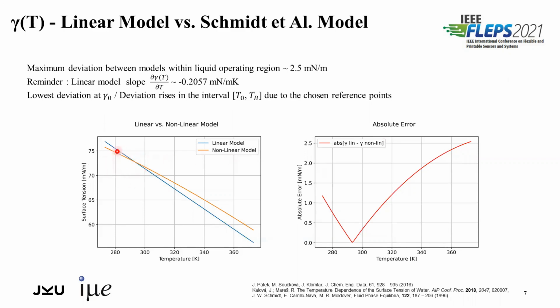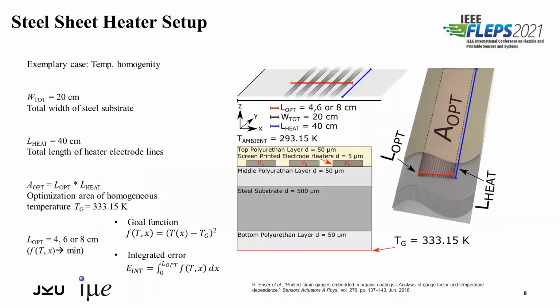And the lowest deviation is in the region of gamma 0, because this is one of the reference points for the nonlinear model. And the maximum deviation here is about 2.5 millinewton per meter, where the slope of the linear model was about minus 0.2057 millinewton per meter per Kelvin. And now to our design.